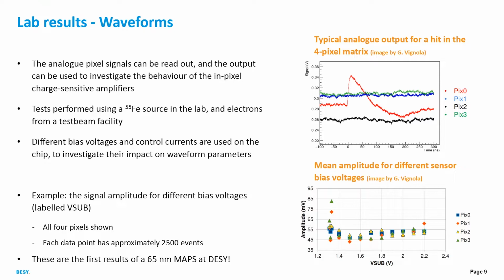We use an iron 55 source in the lab and also electrons from test beams. So this here is a typical analog output for a hit in the 4-pixel matrix. So this is a hit in pixel 0 in the red here, and the other pixels don't see anything. They have a bit different baselines. And in this way we can test how different bias voltages and different control currents impact the waveform parameters.